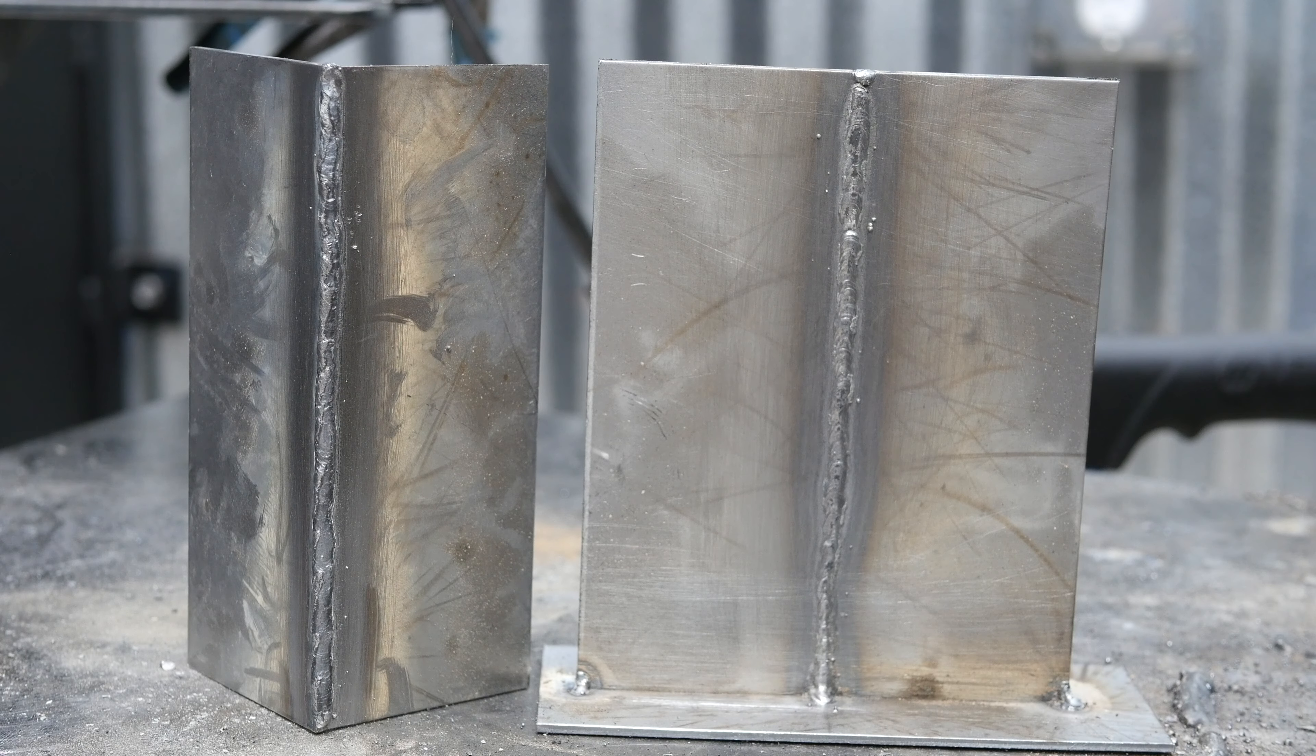Let's break them in half and see what happens. All right, here's the outside corner joint and I stepped on it with my boot and I got it almost flattened out before it broke. This leads me to a really important point about this wire. It does not have very good impact properties. Do not use E71T-11 wire for anything structural, so if it fails and someone could get hurt, this is not the right wire to use. But our plate didn't perform too bad.